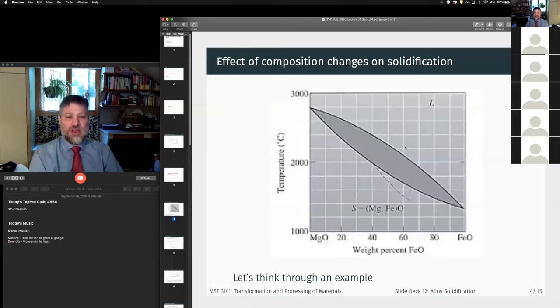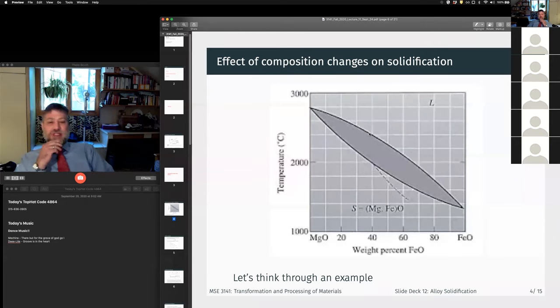Okay. So if we have a single phase, in this case, the magnesium oxide, iron oxide system. If we have this mix of oxides, so we're doing an example in ceramics instead of in metals, and we cool down, we have composition changes on solidification, right? The first important thing to really remember is that we don't have a single melting point. We have a range of temperatures that solidification occurs at, right? So that's important.